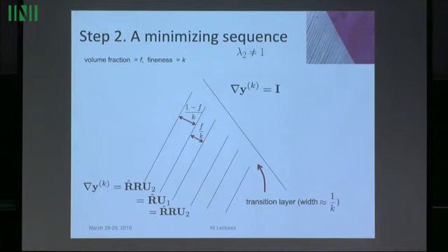Now that requires some conditions. I mean, the R hat has to be chosen also right, and as I said, these other things have to be chosen right. So you work this. This is algebra that I'll talk about later. Anyway, at the end of the day, you can compare with experiment, and the most striking thing is to compare the normal. I said this interface has to be chosen very special. Then you compare the normal to this interface to the measured normal, 37, 45, 23, whatever it is, of this irrational interface, and they agree beautifully. Okay? So that's a great success.